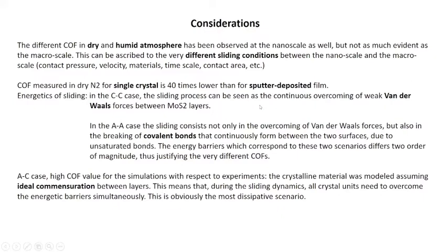So in order to understand this, we have to do some consideration. Related to the difference of the coefficient of friction between dry and humid atmosphere, I have already told you that this is related to the very different experiments. And in the case of the coefficient of friction in dry nitrogen in the single crystal case, we have to consider that in the C-C case, the sliding process is only related to the overcoming of the van der Waals forces.